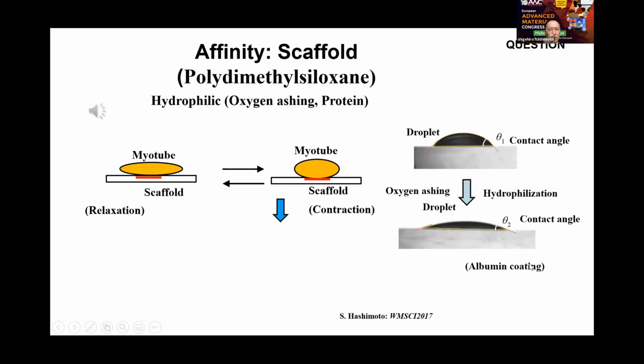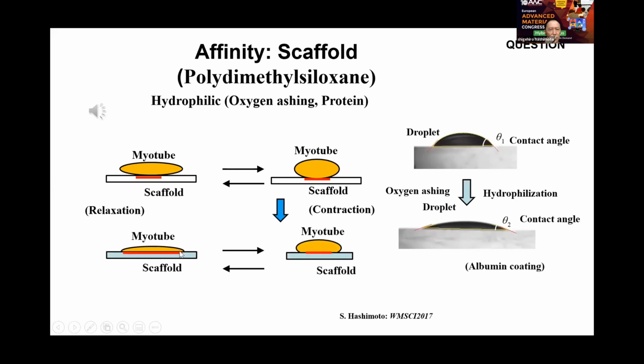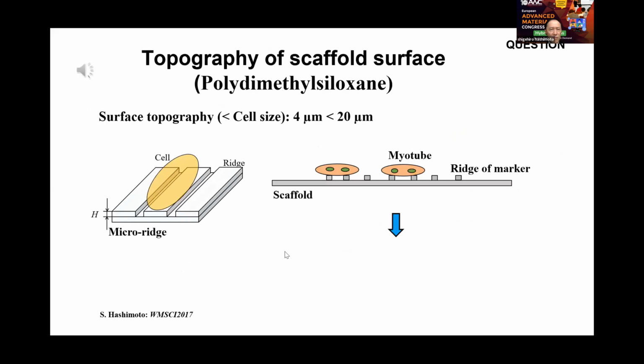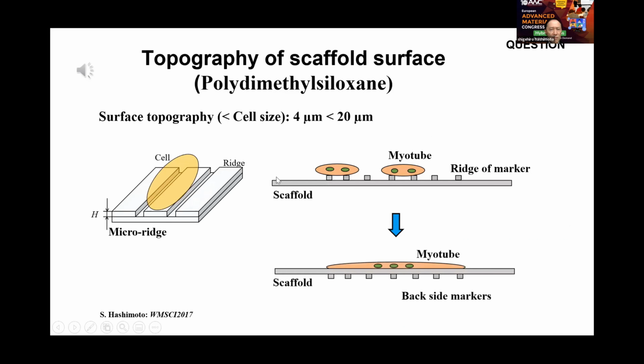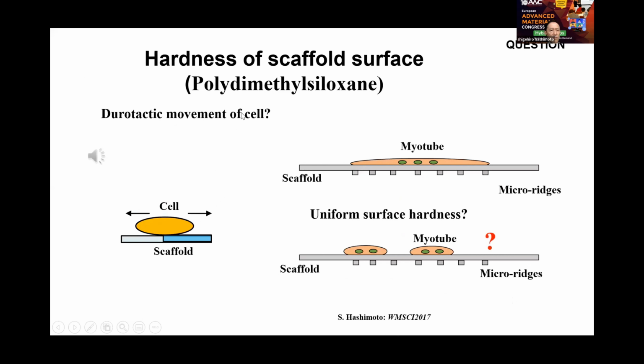Hydrophilicity for cell adhesion. Surface topography affects cell alignment. The protrusion of the surface changes the elastic properties of the scaffold. Does the backside microridge affect the mechanical properties of the scaffold surface? Surface hardness may be related to the durotaxis of cell migration.